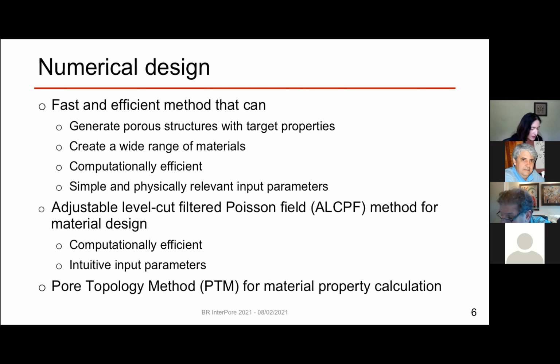It's a long name. It is a method based on Poisson random fields. We use it for numerical design. It is computationally efficient, and it has very intuitive, physically relevant, simple input parameters. And to calculate the final parameter that we're measuring, be it pore size distribution, porosity, or permeability, we're using a pore topology method called PTM that we also developed in-house. So we're coupling these two methods, the ALCPF that we developed specifically for numerical design of porous materials, plus the pore topology method that we use for material property calculation.